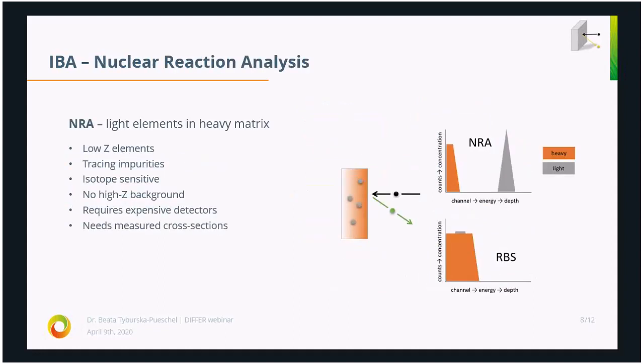Then we have a technique which is called nuclear reaction analysis. It is sort of opposite to RBS. NRA is used if you want to detect light elements in a heavy matrix. That, for example, would be deuterium in tungsten, which is depicted on your right side. This orange is our heavy matrix. Light particles are, for example, deuterium. And then we have this black incoming beam from the accelerator, but in this case there are no backscattered particles. The beam which we register is not the original beam which we used from the accelerator. Those are particles coming from the nuclear reaction.